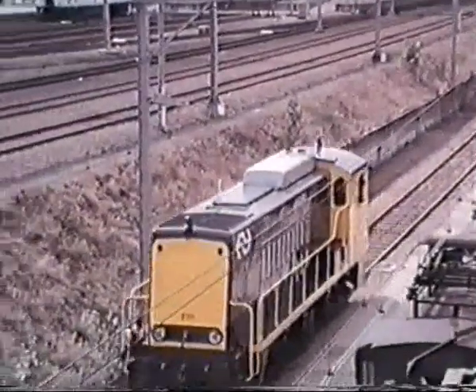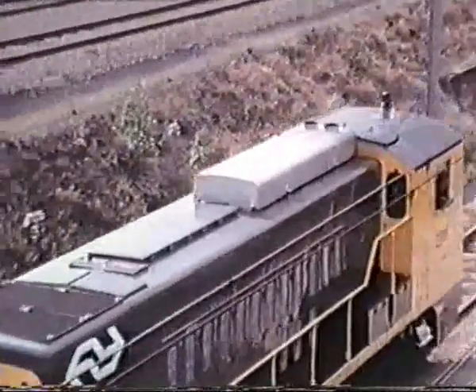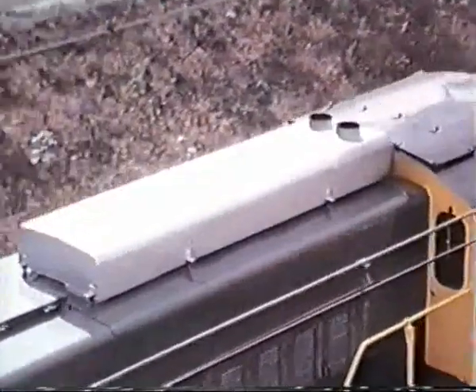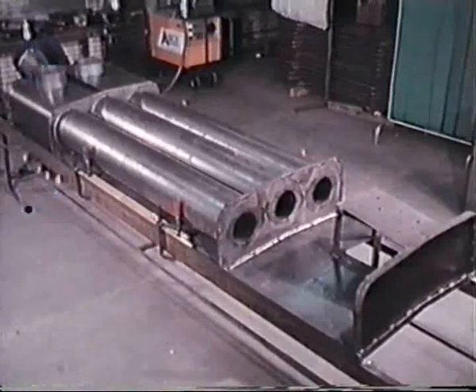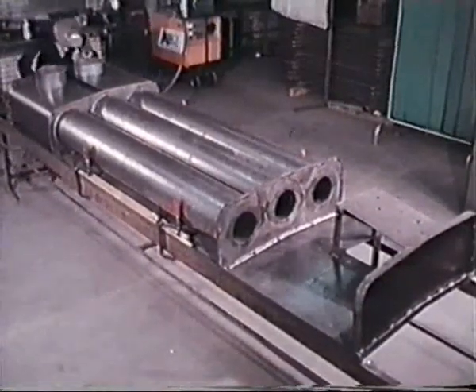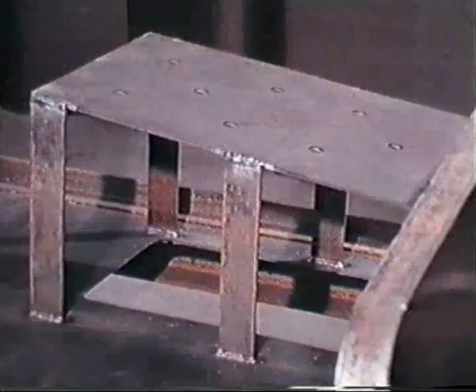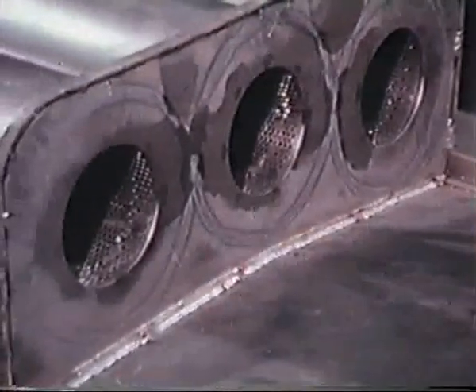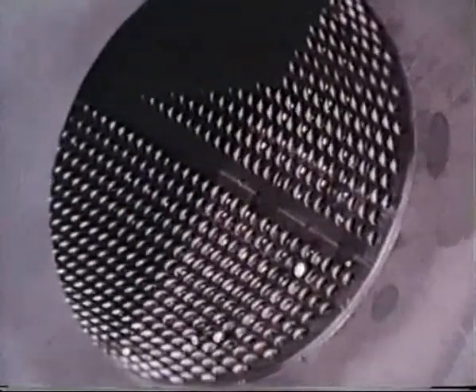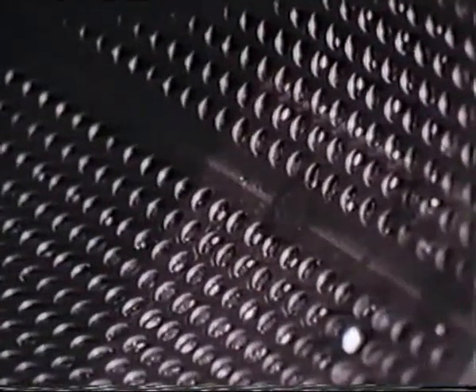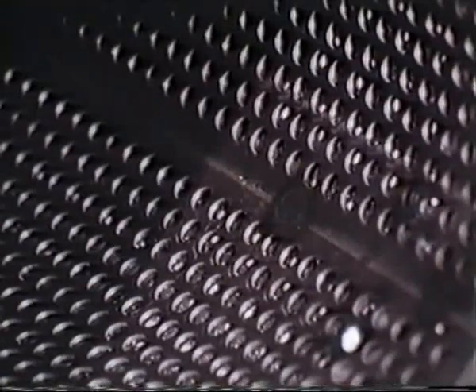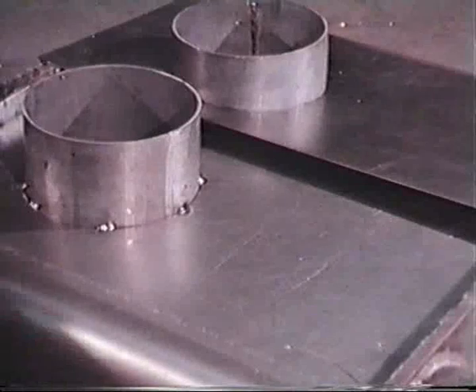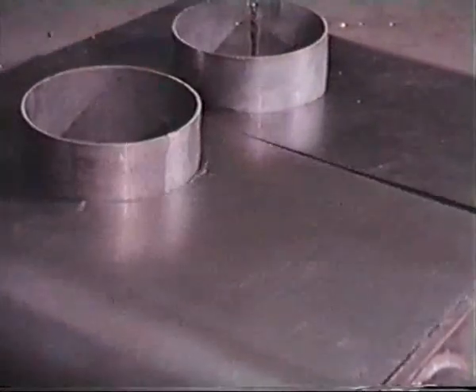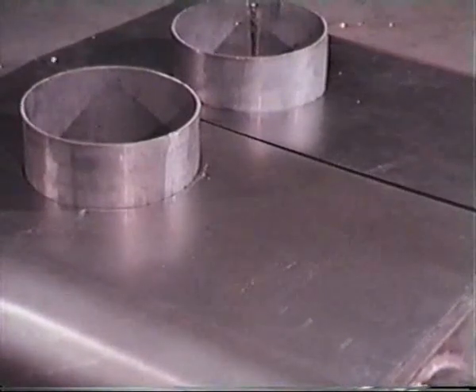Acidic gases can shorten the life of a steel exhaust system. In 6 months, silencers like this were perforated from condensed acid and needed replacement. The system is contained in a thin sheet steel box. To quieten the engine, the hot gases pass into tubes lined with sound-absorbing material. With the train in motion, the cold outside air condensed acids on the metal and allowed rapid corrosion. The problem was overcome by creating a double skin and then putting insulation material in the cavity. A problem solved by design.